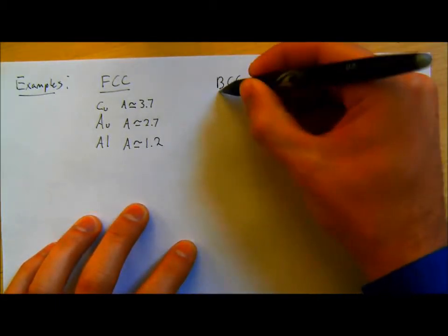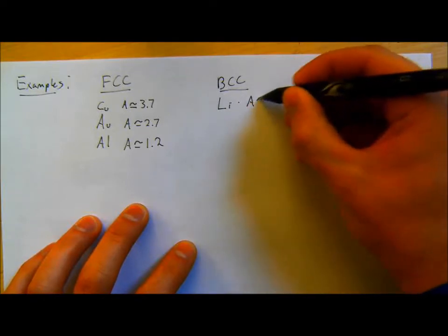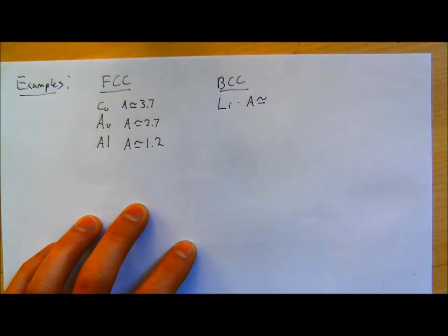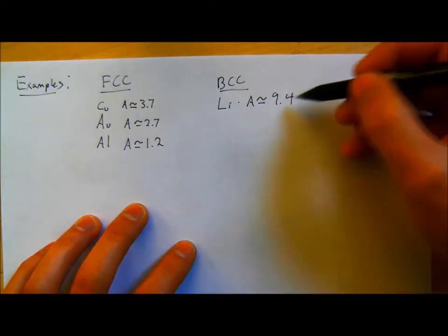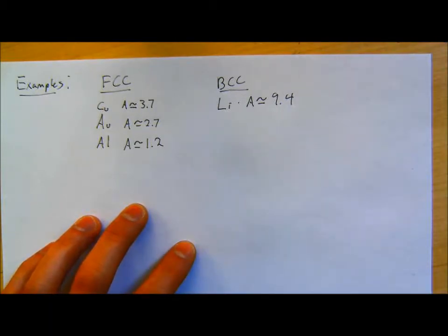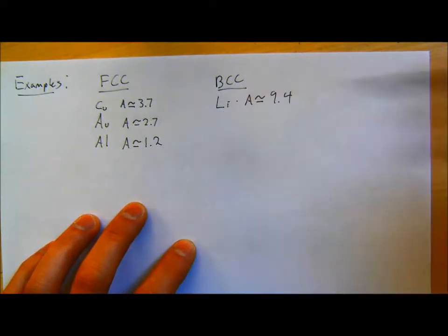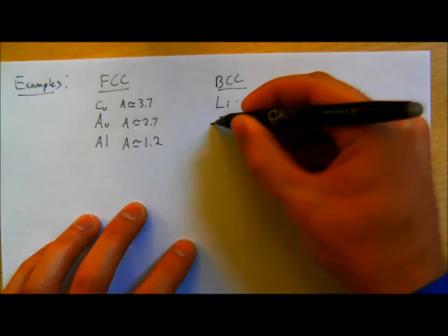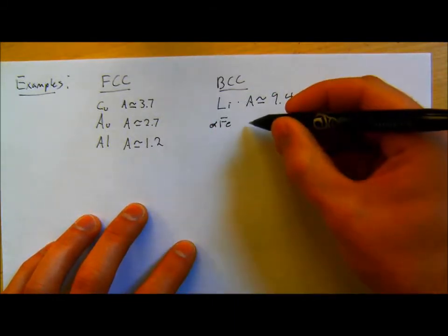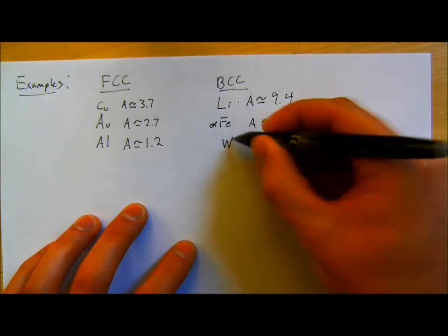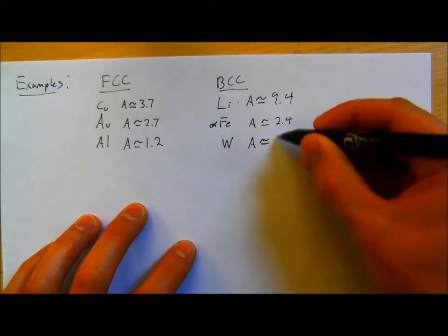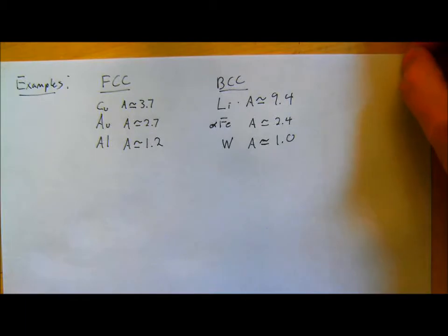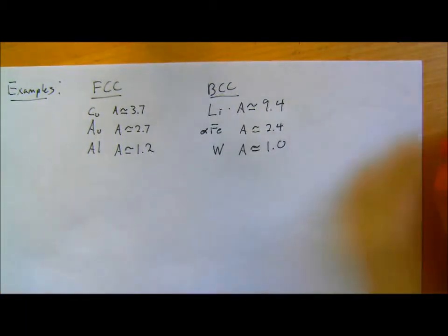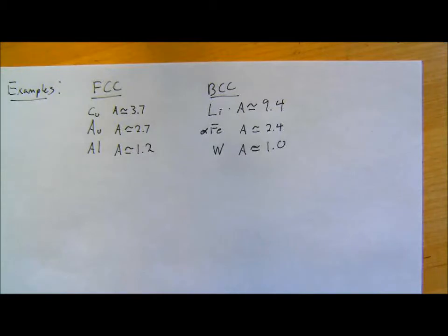For BCC metals, one of the fun ones is lithium, where it's super anisotropic, somewhere on the order of like 9.4. I think I've seen values as high as like 15 for it. Lithium is a very relevant metal for batteries nowadays. Something like an iron, an alpha iron, which is a crystal organization of your iron, A is around 2.4, and for tungsten, which is a W, A is actually pretty close to 1. So there are some materials that are relatively anisotropic, even in their crystalline state, but this is more of a coincidence than anything. It just so happens that based on the atomic interaction of the tungsten ions, it ends up being something around 1.